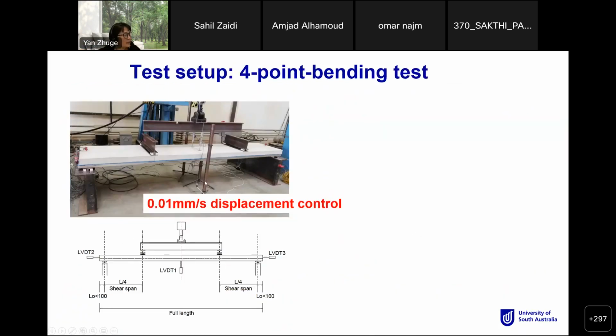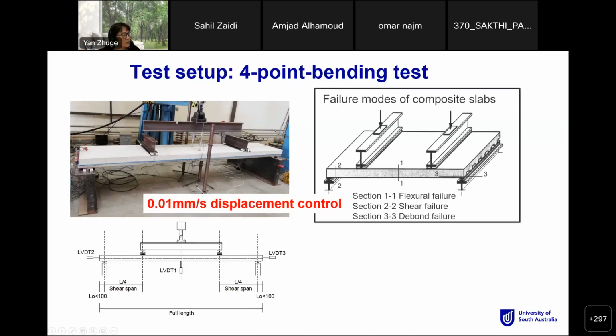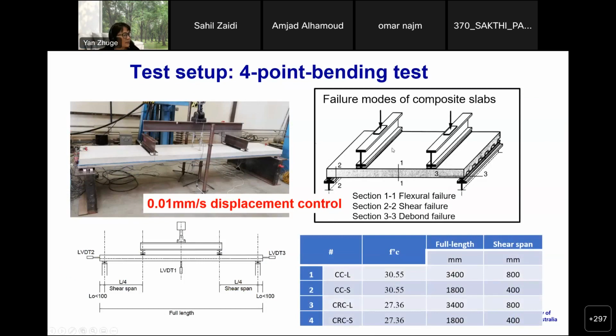So that is the testing setup. Of course, we did the normal 4-point bending test as shown in this diagram, testing setup and testing. So we have a normal concrete long span slab, a normal concrete short span slab, and also a crumb rubber concrete long span slab and a crumb rubber concrete short span slab. So we have two lines of testing. One is 1.8, the other one is 3.4, because we want to see the shear performance as well. So that's why we tried two different lengths. And the shear span of the longer one is 800 mm and the shorter one is half of that, 400 mm.